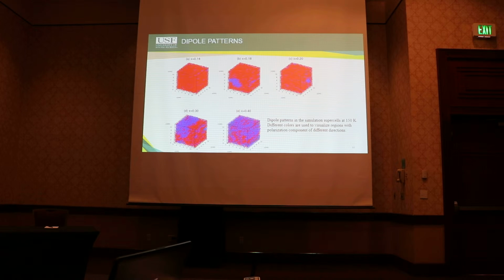At 14%, we see an almost completely homogeneous cell. But at 18 and 20%, we do see some polar nanoregions of cylindrical shape, and this does explain the monoclinic phases that we identified earlier. At 30%, the polar nanoregion grows in size significantly, until at 40%, the cell is completely disordered, signaling a lack of polarization. Oh, and these cells are all at 150 Kelvin.